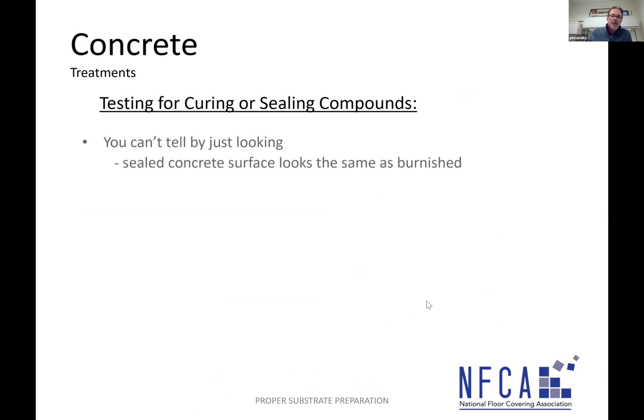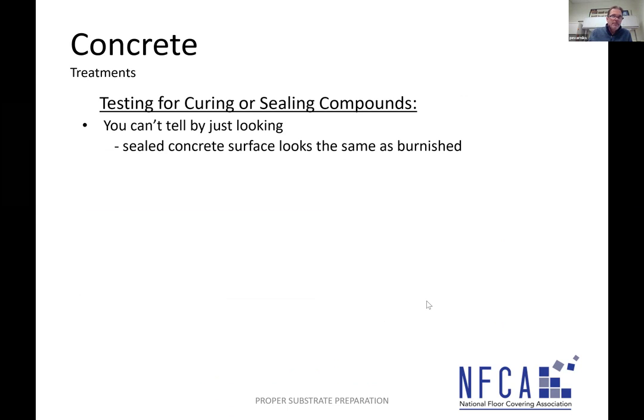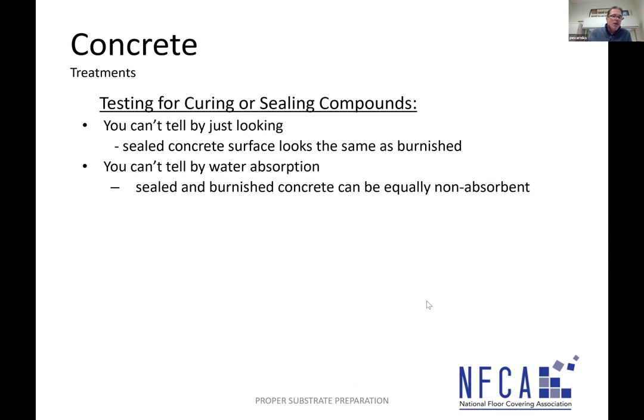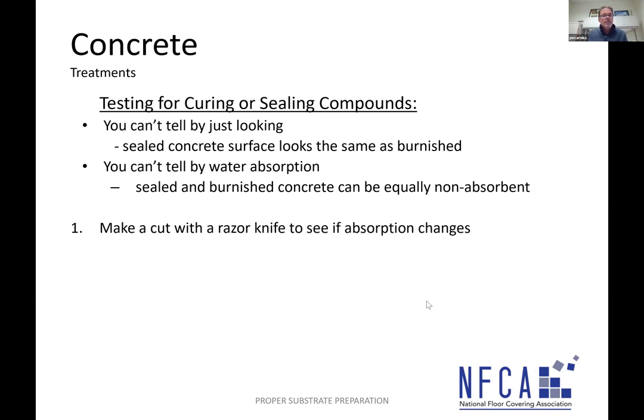Testing for curing and sealing compounds, okay? You can't just tell by looking. We looked at burnished concrete. We looked at concrete with a cure and seal. We really couldn't tell the difference. You can't tell by doing water absorption testing either, because if it's burnished concrete, water doesn't want to soak into it. If it's a sealed concrete, water doesn't want to soak into it. Okay, so what do we do? We make a cut with the utility knife. We see if the absorption changes.